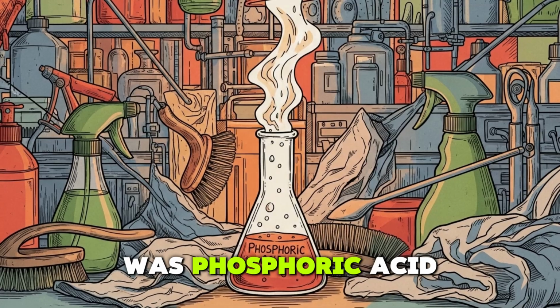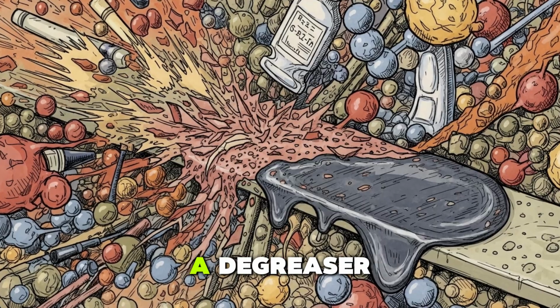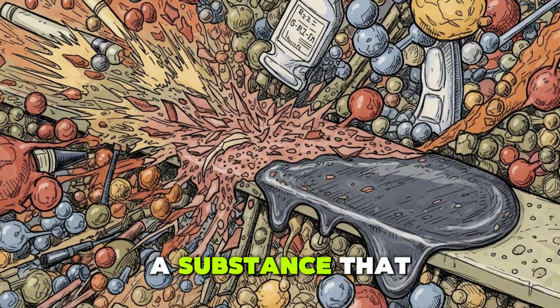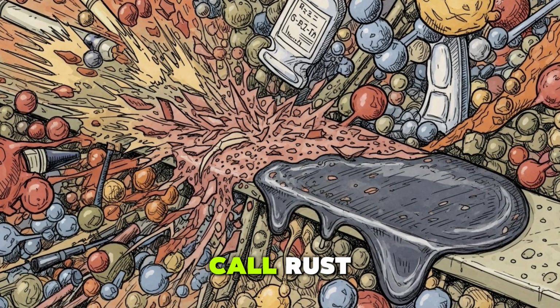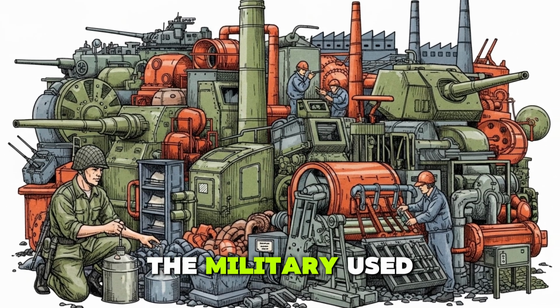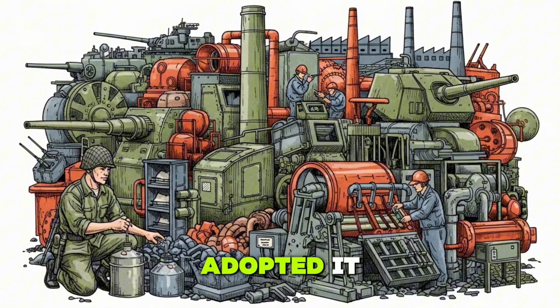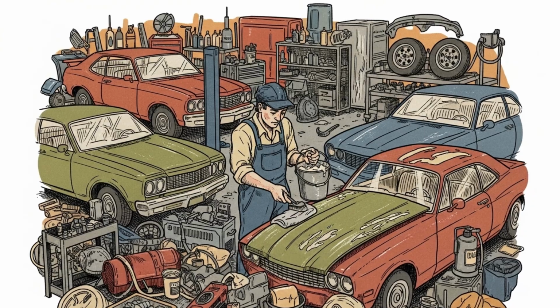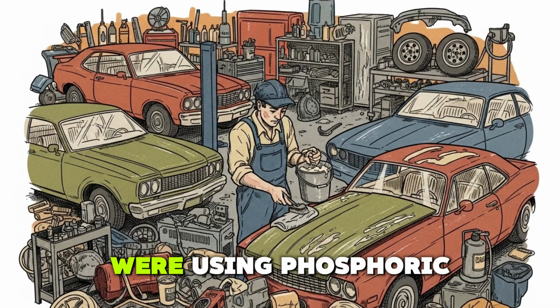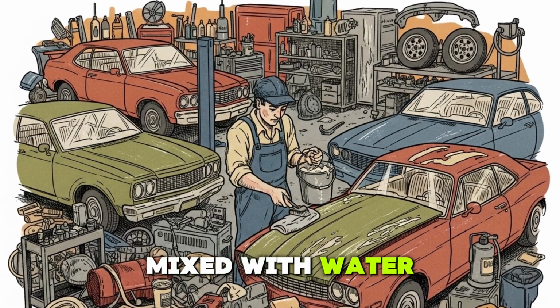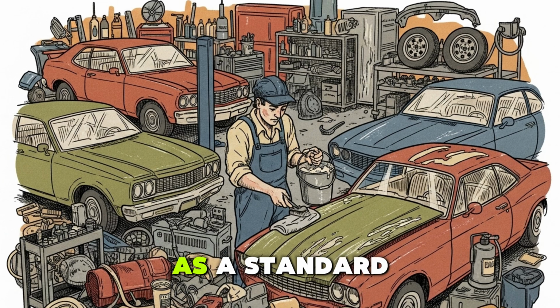What they discovered was phosphoric acid. Not as a cleaner, not as a degreaser, as a converter, a substance that reacts directly with iron oxide, the compound we call rust, and transforms it through a chemical process into iron phosphate, a stable, dark, tightly bonded compound that adheres to the metal surface and actually seals it against further oxidation. The military used it. Industrial manufacturers adopted it through the 1950s and 1960s. Body shops in the American Midwest were using phosphoric acid solutions mixed with water and applied by brush or rag as a standard pre-paint treatment well into the 1970s.